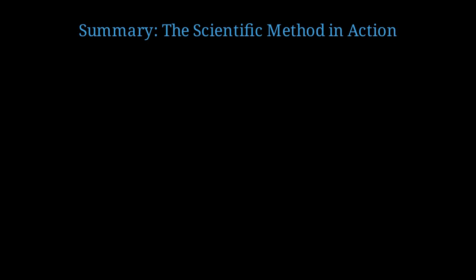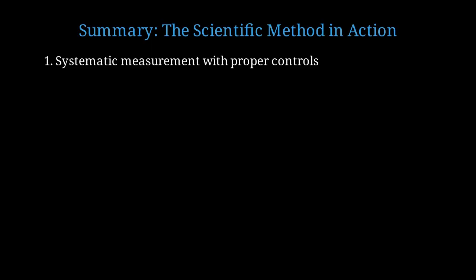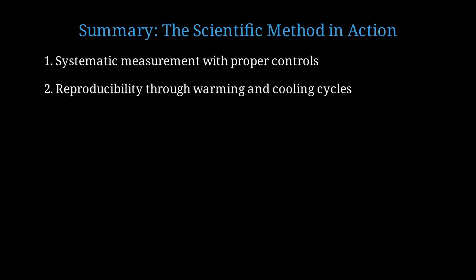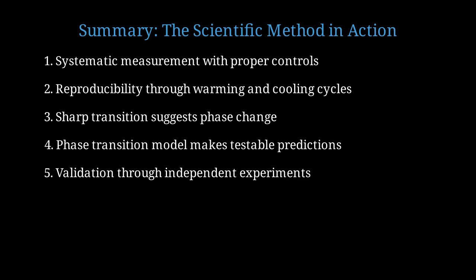Let's summarize what we've learned about the discovery process and the scientific method in action. First, systematic measurement with proper experimental controls. The 4-point probe method was essential to eliminate artifacts. Second, reproducibility through multiple warming and cooling cycles. This confirmed the transition was a real material property, not an artifact. Third, the sharp transition width suggested a thermodynamic phase transition rather than a gradual crossover. Fourth, proposing the phase transition model allowed us to make testable predictions about critical fields and critical currents. Fifth, validation through independent experiments confirmed the model and revealed new physics.